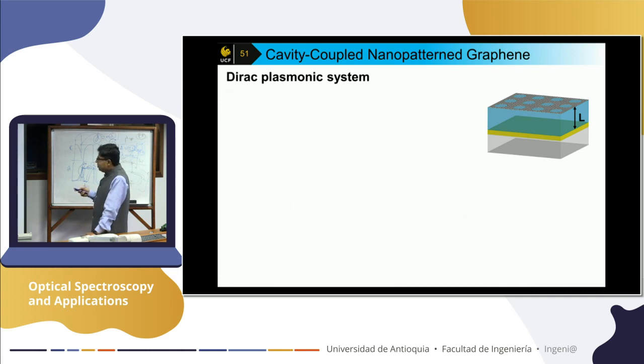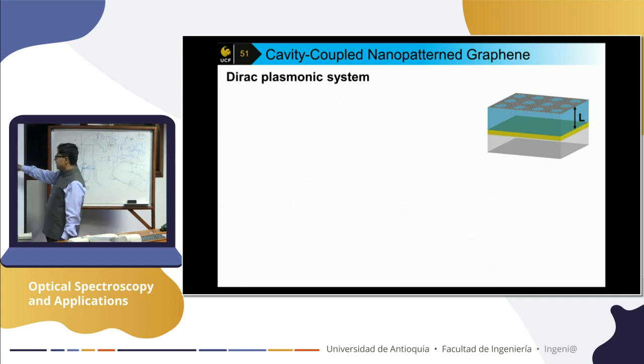You can actually pattern graphene. Because graphene doesn't absorb light, people did some metal patterns to create plasmon resonance, and when light comes in, you excite the plasmon and light gets absorbed. But as I always said, when you add a metal on top of graphene, the energy gets dissipated in the metal, not in the graphene. Our goal is to have the energy dissipated in the graphene, not the metal. So we didn't add any extrinsic material, simply a pure patterned graphene film.